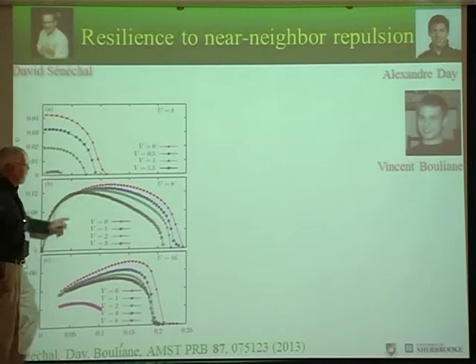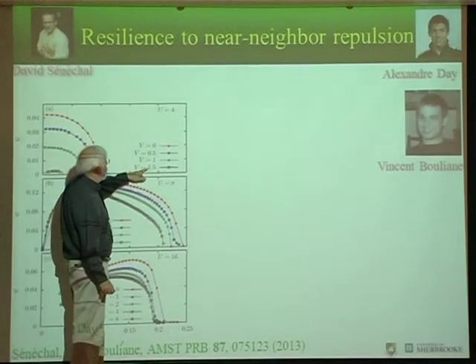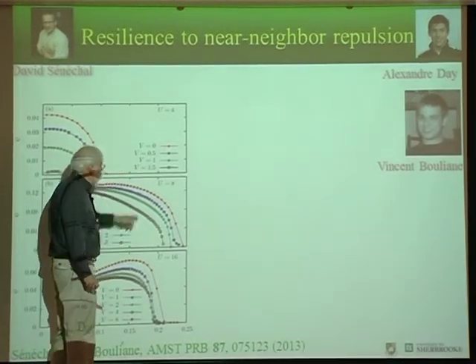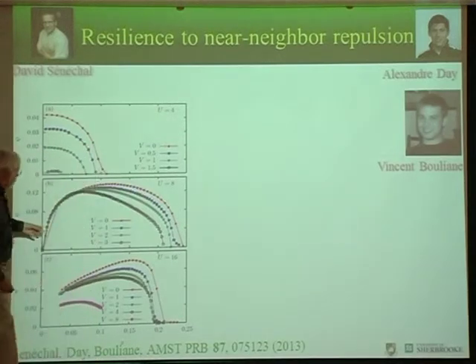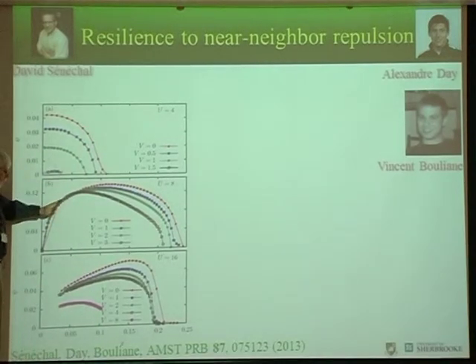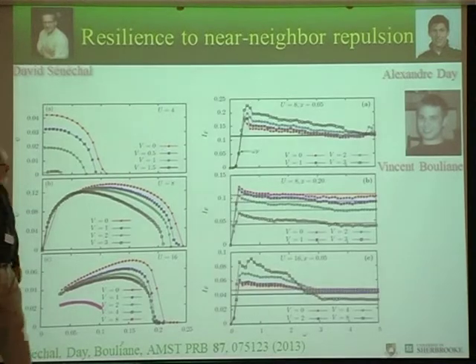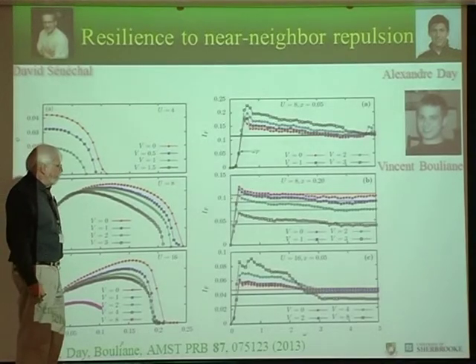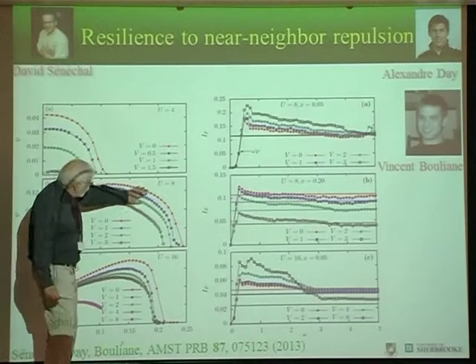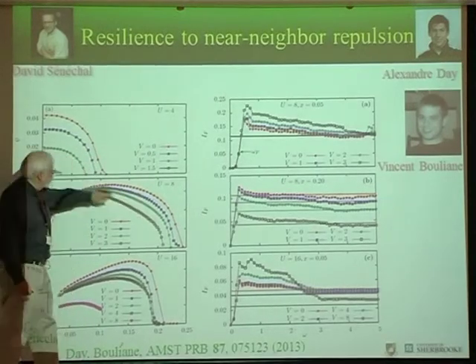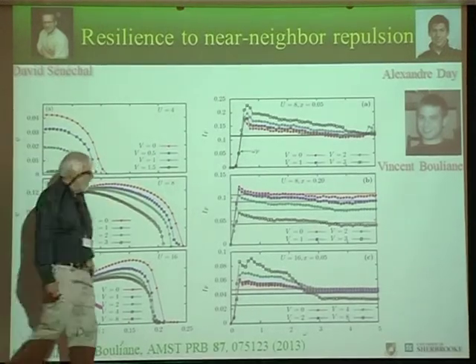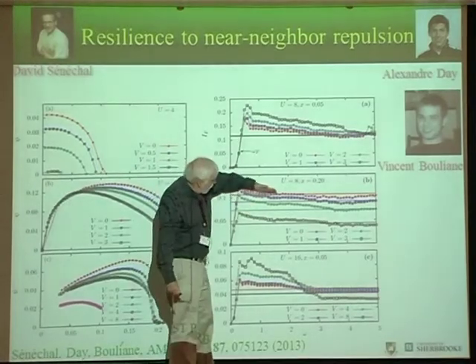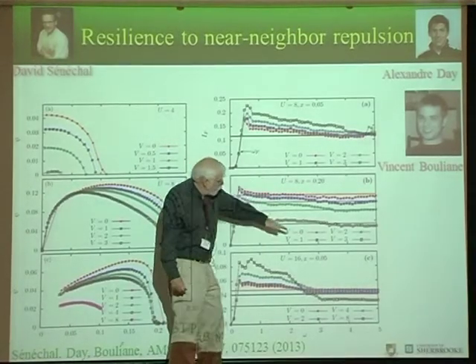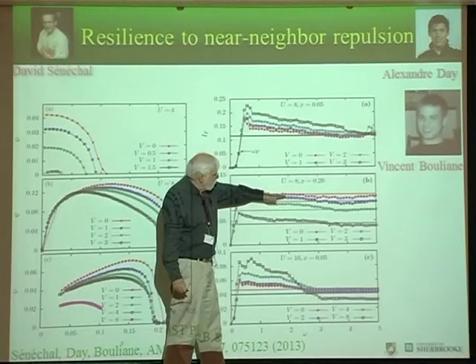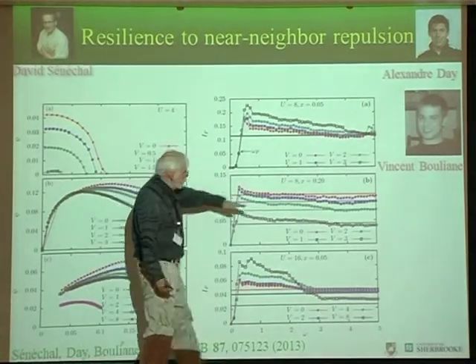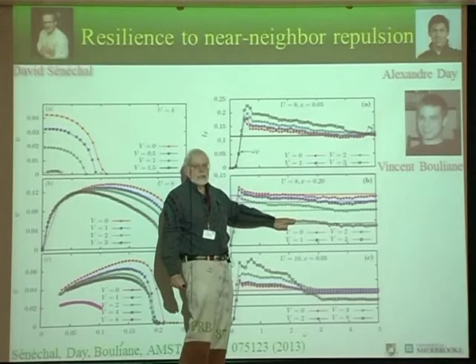It's quite resilient. In fact, if you look at this ratio, 1.5 over 4 or 3 over 8, it's the same ratio. And here it kills superconductivity. Here it does nothing. So if we look at this cumulative order parameter, you see that in this overdoped region, where it's more sensitive to V, a little bit like at weak coupling, V equals 0 is this red curve. And as I go to the black curve with V equals 3 in this overdoped region, you see that everything always goes down.